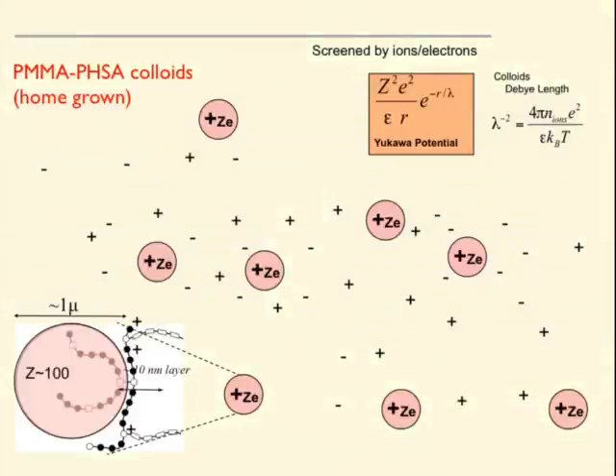So first, I should say that what's happening in the system is the particles are charged over here. They repel one another. They're 1 micron particles. The charge on each one is something like 100 charges. And the interaction between the particles is not a direct Coulomb interaction because these counter ions, everything that you deal with, including your body and everything, is charge neutral. You know that. If you don't have charge neutrality, the electrostatic forces are enormous. They'll blow you apart.